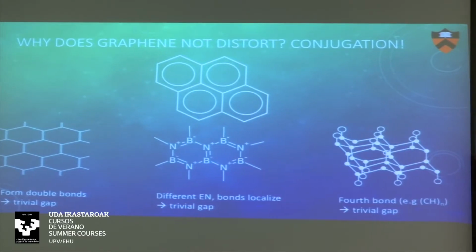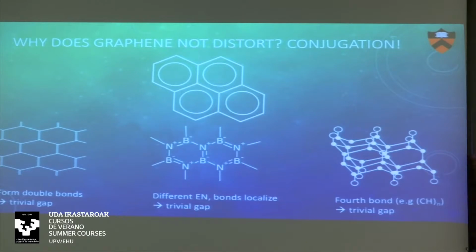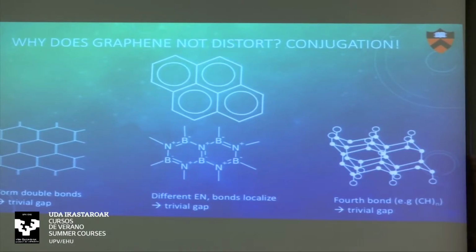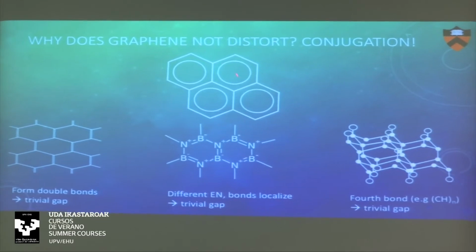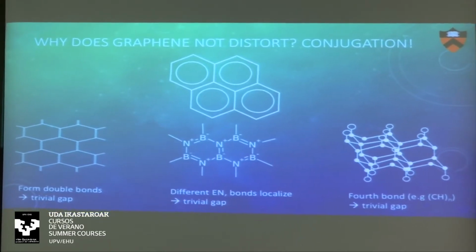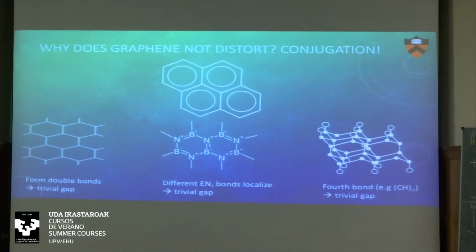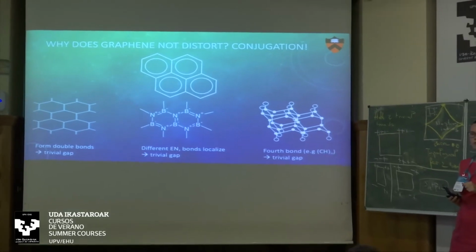And so basically a chemist says this aromatic delocalized pi stabilization is what causes the electronic structure of graphene, and physicists say the hexagonal symmetry, or the symmetry protection, causes this, and it's the same thing, right? Because one determines the other. The thing is that this kind of aromatic delocalization is very unique to carbon. Carbon is known to bond to itself. It's known to have pi bonds that delocalize. No other element is known to do that.